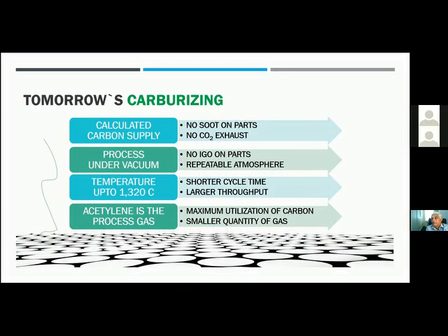But keep in mind, these come with a caveat. And the caveat is that the steel has to be different. You need to ensure there is sufficient vanadium, nitrogen, and aluminum in the steel. Those doping agents are needed. Otherwise, you end up getting a lot of grain growth in the steel, and you don't accept that. So yes, high temperature carburizing is possible. Cycle times can be reduced.